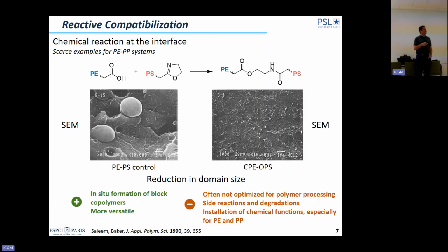So another option is to do a reactive compatibilization, and I will give you one example. In this case, we want to create bonds at the interface during the processing, ideally. If you can do this by reactive processing, there is no need for a solvent. And ideally, you would not want to change the process which was used to process the plastics. So here, for example, you have a polyethylene which is terminated by a carboxylic acid function. You have a polystyrene with an oxazoline function, and you can react the carboxylic acid with the oxazoline, and you create this amide bond, and you connect the PE and the PS, and you make in situ the block copolymer, which will be your surfactant, which will be used to improve the compatibility or to decrease the interfacial tension.